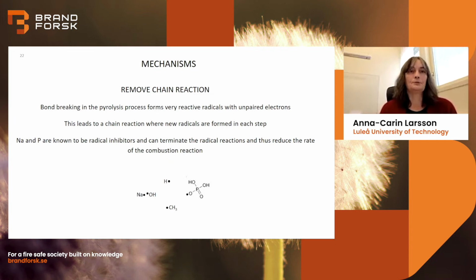We can also remove the chain reaction. So if you remember, this bond breaking from the pyrolysis forms those reactive radicals with unpaired electrons, which then want to react quickly to pair the electrons, and then we get the chain reaction. But sodium and phosphorus are known to be radical inhibitors, so they can terminate those radical reactions, so that will reduce the rate of the combustion reaction.